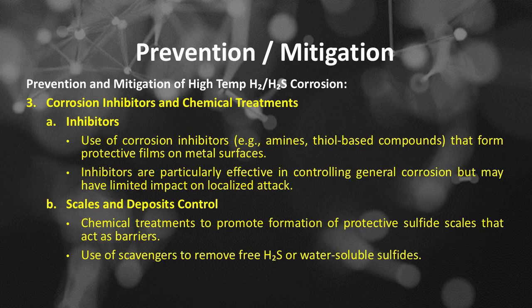Number 3 of prevention and mitigation methods is corrosion inhibitors and chemical treatments. A: inhibitors. Use of corrosion inhibitors, such as amines, thiol-based compounds, that form protective films on metal surfaces. Inhibitors are particularly effective in controlling general corrosion but may have limited impact on localized attack. Number B, scales and deposits control. Chemical treatments to promote formation of protective sulfide scales that act as barriers. Use of scavengers to remove free H₂S or water-soluble sulfides.